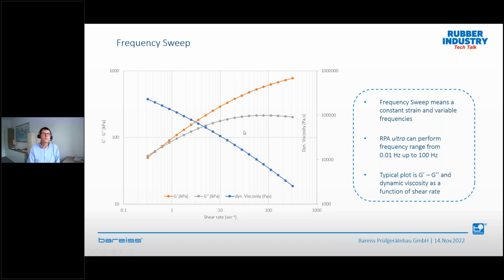For example, the RPA Ultra can perform from 0.001 up to 100 hertz, but a typical one starts at 0.01 hertz, because 0.001 needs a lot of time. And this is something where we definitely can produce very nice results. A typical plot is G prime, G double prime and the dynamic viscosity. And that is what you see here in the graph.